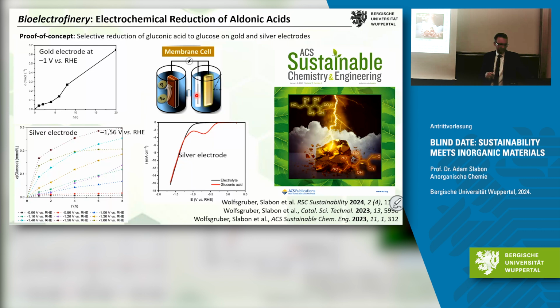In theory, you use a working electrode made of gold. It's the same game with green electrodes, and you make the reduction. Then she also tried silver, making a CV with different potential points, so you can see the outcome. The glucose production is at its maximum, and she found it at -1.5 volts.